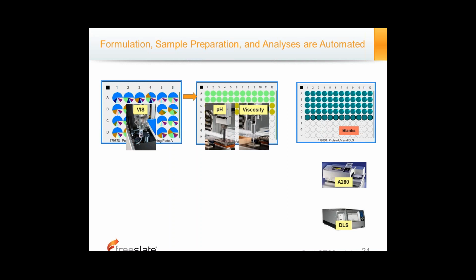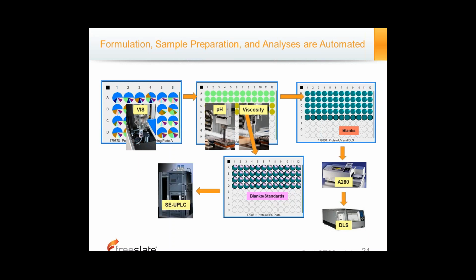And now we can take the material and create blanks and samples for the UV vis. We can either make 2 different plates, or we can conserve material and use 1 plate to do both the A280 and, if you want, you can do the A350 as well as the DLS. And we can also take material either from one of the original aliquoted plates or from the original vials and start to perform SEC. Again, we can select from the best performers early on to minimize the amount of downstream processing and analysis, or you can process all of them.